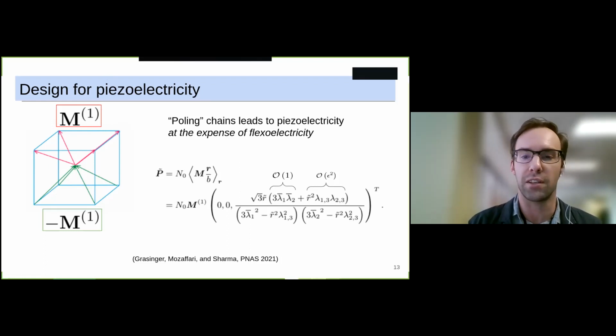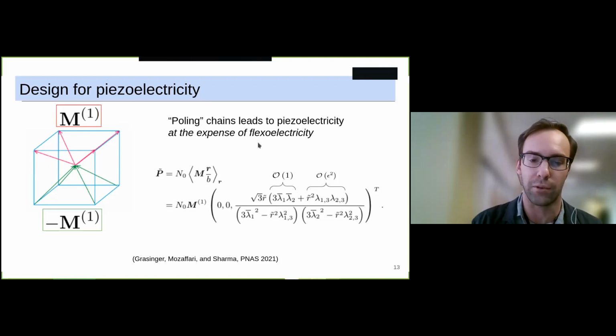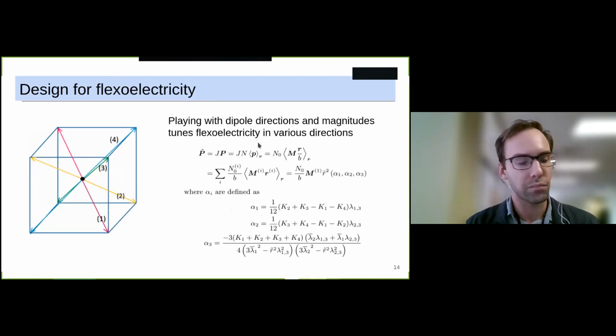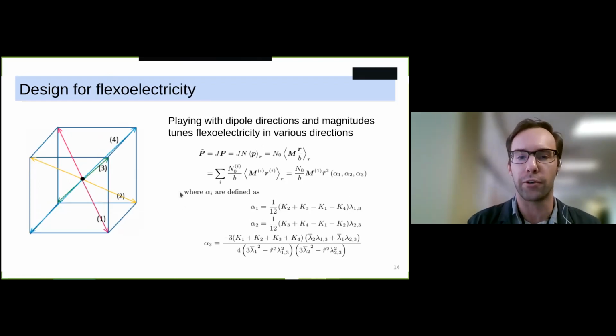And what's interesting is that there's this trade-off. You can enhance the piezoelectricity, but it's at the expense of the flexoelectric effect. There's no free lunch here. And we can push this a bit farther. We can instead think about specifying the directions of the dipoles along the chains for each of the 8 chains in the unit cell.